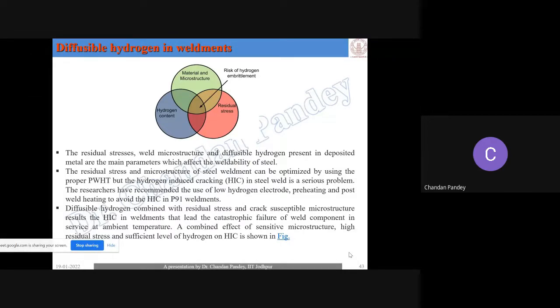The third important parameter is residual stress. Residual stresses come due to two things: either the application of high heat input, and second, metallurgical transformation. Suppose your base metal has austenite, and after heating and cooling it transforms from austenite to martensite. Austenite has an FCC structure, and martensite has a body centered tetragonal structure. If we change from FCC to BCT, we get lattice distortion of the structure. Due to that lattice distortion, we get some amount of strain in that region, and due to that strain we get some amount of residual stress.